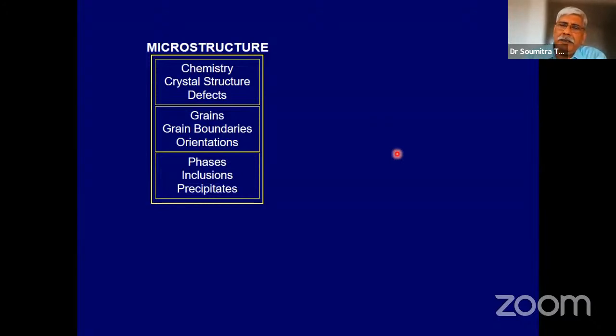You can define a metallic material by its microstructure, by its chemistry, crystal structure, the defects that it contains, the grains, grain boundaries, or the orientations of the grains that you have in the structure, the phases that are present, or some of the inclusions and precipitates that are there in the structure. So all these help us to define a metallic microstructure.